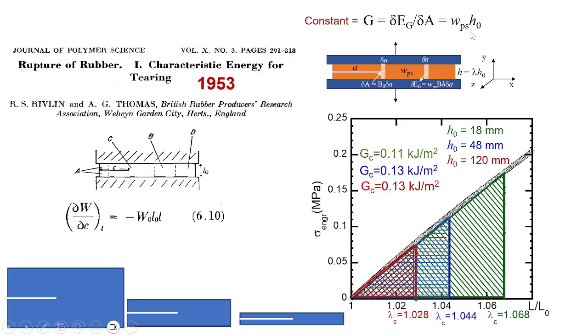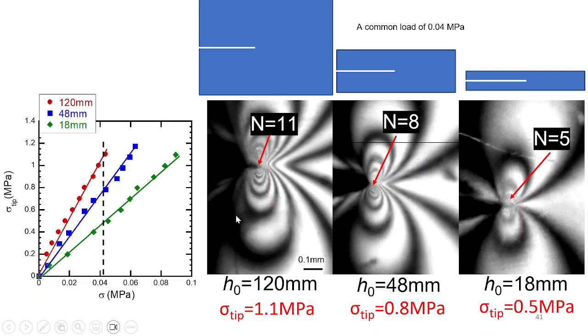I had a different insight. I judged that this occurred because when the crack occurs, the tip has reached the same stress, overcoming the strength of the material. So it turns out we can just repeat this experiment using 3 different heights. We find indeed what you're supposed to see. In other words, if you load your sample with different heights to the same overall load, you find the tip is much more intensified when the sample is taller.